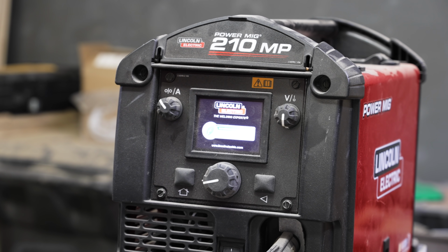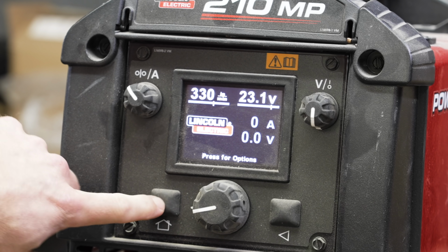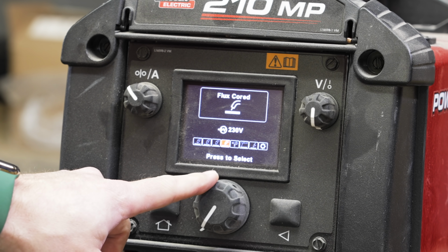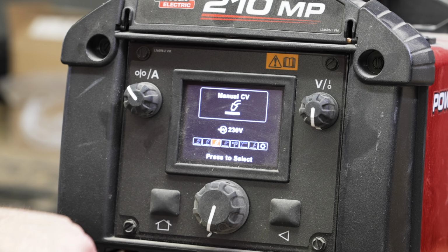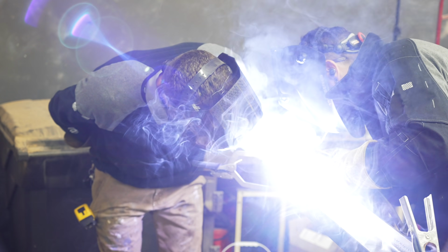Once that was done, I could get the machine settings dialed in, and you need to use the manual CV mode on this PowerMig machine for this type of welding, since they don't have a dedicated dual shield flux core mode. And I started with the settings at 300 inches per minute of wire feed speed and a voltage setting of 21 volts, and then Jamie and I could start doing some welding.